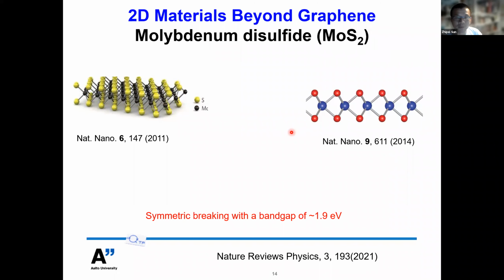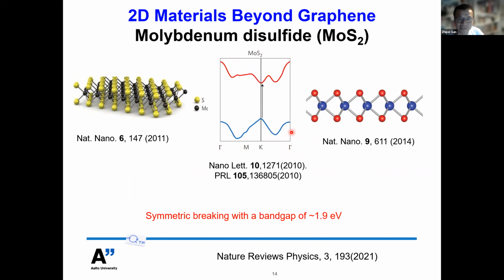Another advantage of using MoS2 is that MoS2 has this unique direct band gap structure when the thickness goes to the monolayer. So that means you can have a certain transparency window for the near infrared light input, so you are able to get a much more efficient nonlinear response.